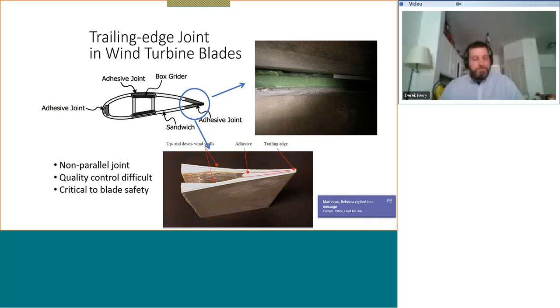This is a cross-section of a wind turbine blade, but it will be similar for a tidal turbine blade. When you have closed the molds, there are going to be adhesive joints in different places, as you see there. In particular, when you have put a thick layer of resin to create the trailing edge joint, if you cut open and see, there will be lots of voids. There will be a lot of gaps between the shell and the resin itself. That is going to cause delamination, as you can probably see in that picture.